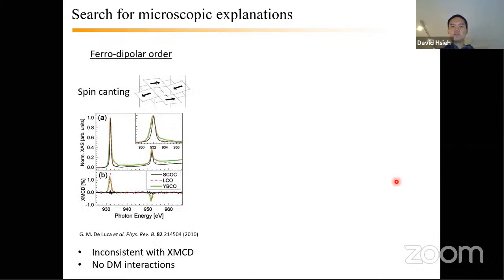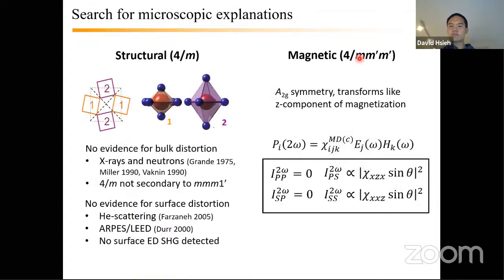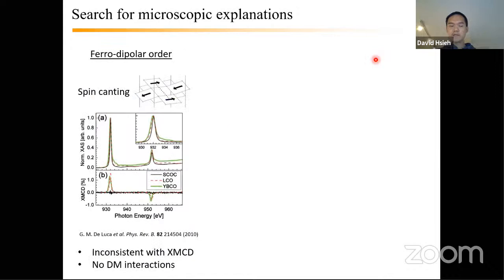Now that we understand what process is generating the observation, our last step was to ask why the system would have this 4/m, m', m' symmetry. That's different from the reported Néel structure. Well, as I mentioned, one possibility is just ferromagnetism. That would do it. So how would you get it? Well, for example, if there's some spin canting along the z-axis, you would have a net ferromagnetic moment. That could explain things.